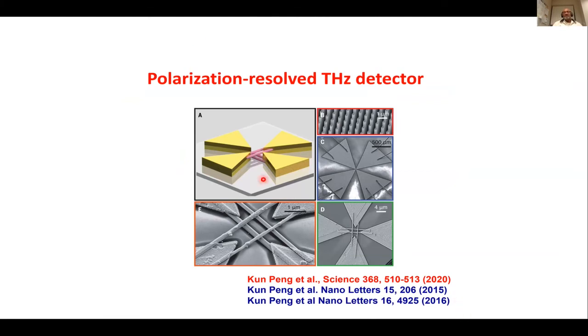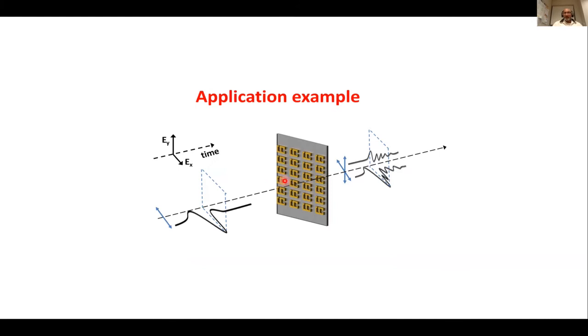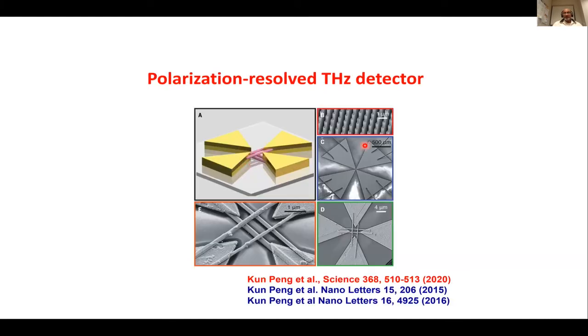But again, to cut the long story short, let me share with you the most current results, where last year we demonstrated a polarization resolved terahertz detector. Instead of using a single nanowire detector, she tried to fabricate, during her postdoc at Oxford, these nanowires which are in an orthogonal direction, 90 degrees to each other, to connect to these metallic bow tie antennas, for example. After growing the structures at the ANU, we sent them to Oxford. She fabricated jointly with Oxford and ANU, and then Strathclyde University.